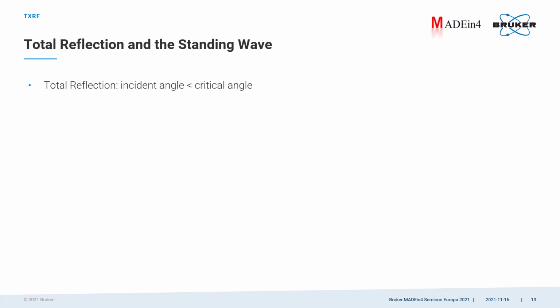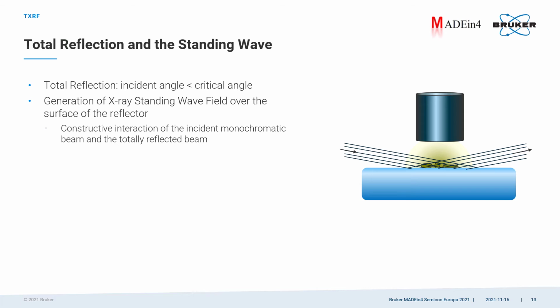The principle of TXRF is very similar to XRF. We hit the sample with an X-ray beam and we measure the fluorescent photons with an SDD detector. Now there are two big differences. First, with TXRF we use a monochromatic beam. In micro XRF it is a polychromatic excitation. The second big difference between the two is the incident angle of the X-ray beam with respect to the sample surface.